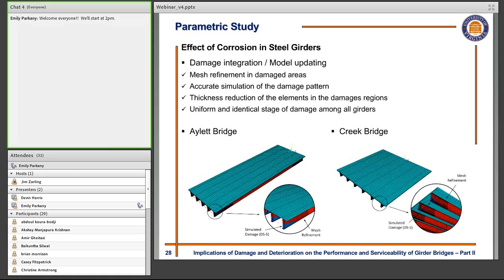So with that, we moved along with the parametric study, and we started to investigate the impact of corrosion in steel girders on these specific structures. For both of these structures, we created numerical models in the same approach, in the same methodology that we used and validated in phase 2 of this project on both the Aylett and Creek Bridge. In order to integrate the effect of damage, we refined the mesh generation at either end of the structure, and this mesh refinement allowed us to model the exact geometrical detail of the damage area.